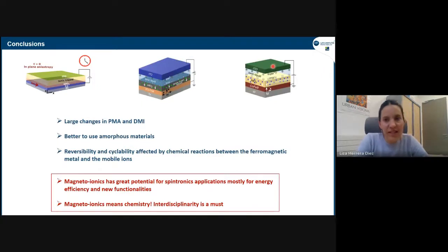So this is really what I wanted to show you today. I wanted to show you an overview of what's being done, an overview of our results. I hope I could show you that with magneto-ionics, we can generate large changes in perpendicular magnetic anisotropy and DMI. That it also seems to be much more efficient in amorphous materials with respect to crystalline or polycrystalline materials. And also that reversibility and cyclability can be very much affected by the chemical reactions that are happening due to the ions moving around in the system.